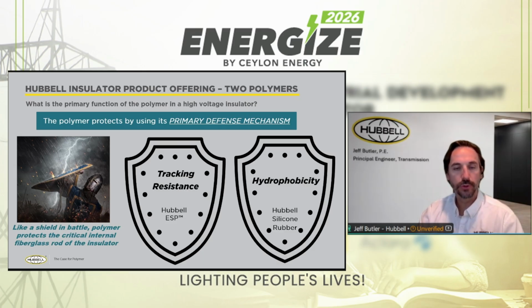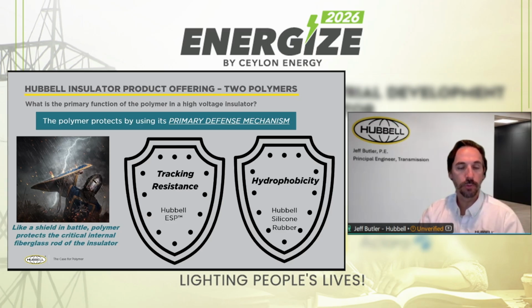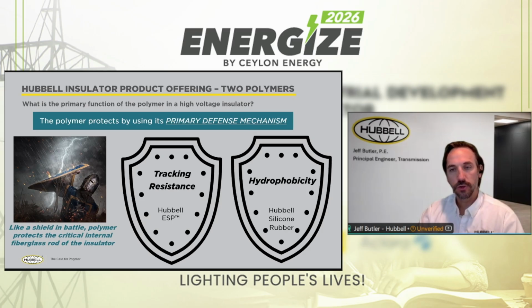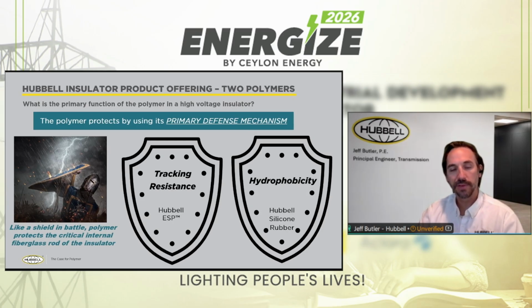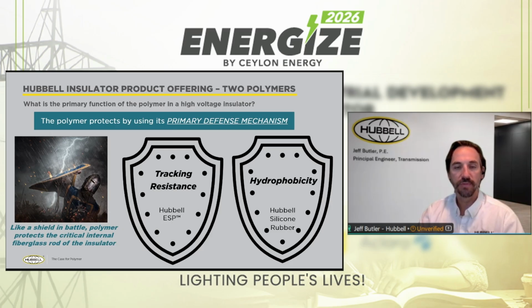So for Hubbell, we use two different types of polymers. I have two shields represented there. The one in the middle of the screen I'm referring to as the Hubbell ESP. ESP is an acronym that Hubbell uses to define our distribution or our ethyl-based rubber. It stands for Enhanced Silicone Polymer, and it's an EPDM, or ethylene propylene diene monomer, blended with a silicone rubber that creates a polymer alloy. The primary defense mechanism for that material is tracking resistance. It is very tough. It is a durable material. Even if electrical activity is occurring on the surface of the rubber, it's going to be able to withstand that electrical activity for a long duration.